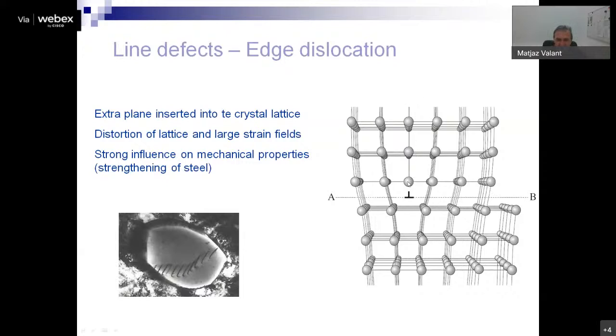So this one here is dislocation, and we can see dislocation sometimes already with the optical microscope, because again it creates a significant strain field around the dislocation. So this is what we actually see here. We don't see the dislocation itself, but we see the strain field. Now, this has got a very strong influence on mechanical properties. Let me tell you, we will discuss this later in detail when we talk about mechanical properties, so we can leave it like that now.